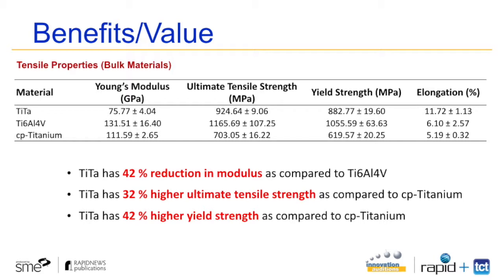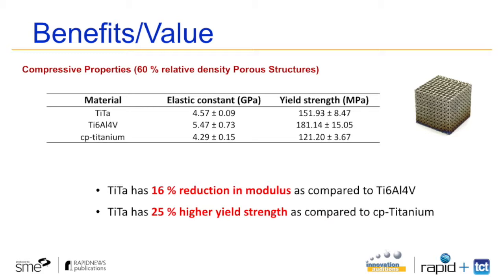So we benchmark this titanium tantalum alloy that is produced with conventionally used Ti-6Al-4V, which is very popular in the market nowadays, and pure titanium. And we actually see improvement in mechanical properties and performance, such as a 42% reduction in modulus, which is a reduction of modulus stiffness and brings it closer to human bone, while maintaining a higher mechanical strength compared to pure titanium. Even in lattice form, we also observe a similar trend in improvement in mechanical properties compared to pure titanium and Ti-6Al-4V.